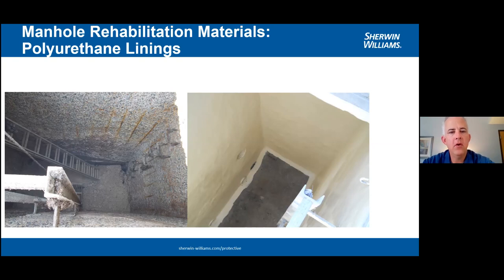If you'll notice on that photo on the left, again, you see the exposed rebar. We had lost about 2.5 inches of concrete in this structure as well. So after we did the clean out, wash out, this is what we were starting with, what you see on the photo on the left. We used a microsilicate repair mortar to bring everything back up to the original plane and give it the structural integrity that the engineer designed this structure to have. We replaced the concrete back solid like it was supposed to be, to a uniform surface.